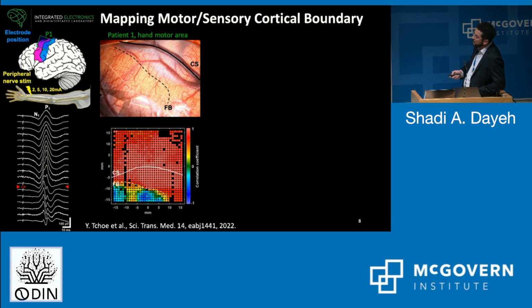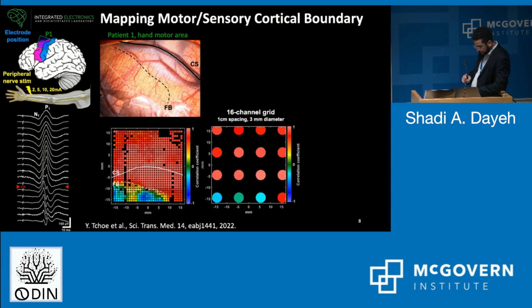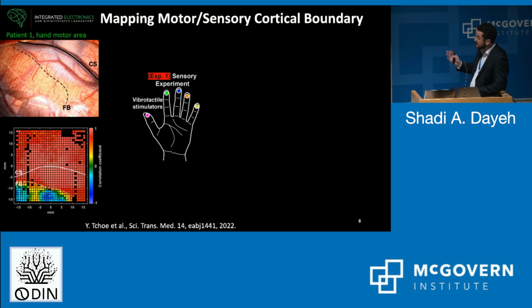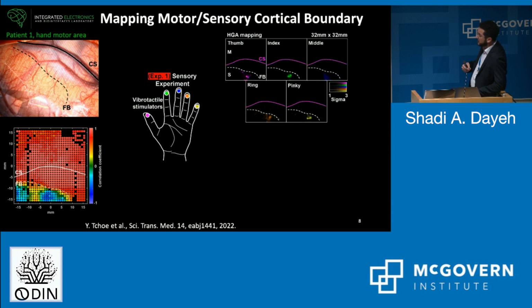Applying the platinum nanorod grid, we were able to observe the curvilinear nature of this functional boundary and show that it is indeed curvilinear at a millimeter scale. Now, with the clinical approach, usually a lot of linear interpolation is done, and we'll not talk about the surgical implications of that, but we'll talk a little bit about some of the behavioral experiments that will fit into this context. So first, we put vibrotactile stimulators on the fingertips and evoked activity across each one of them. And this stimulation evoked activity in the somatosensory cortex below the functional boundary that we have identified from the first experiment.